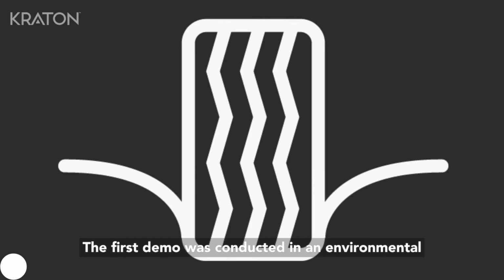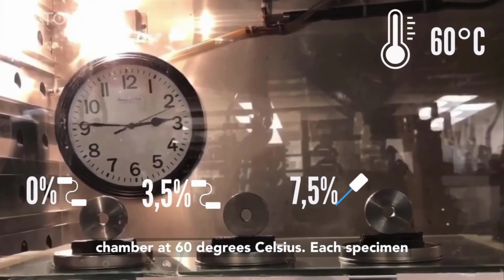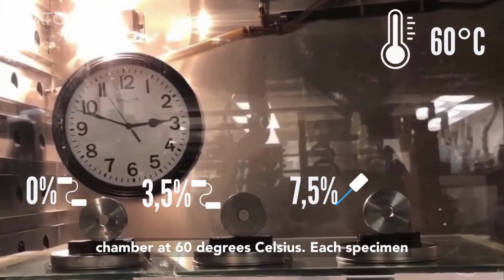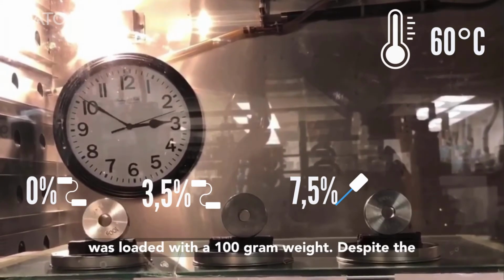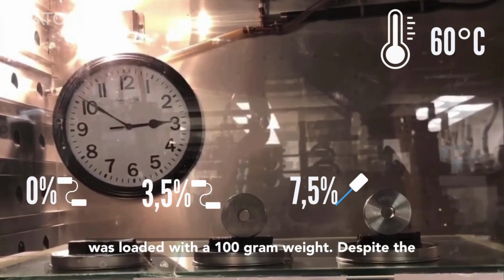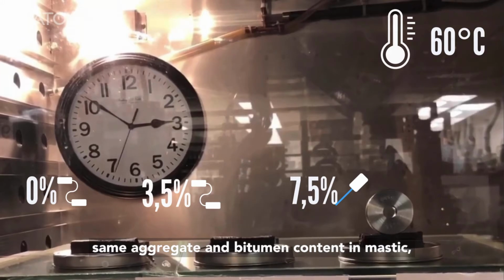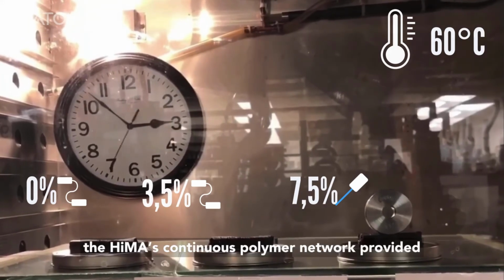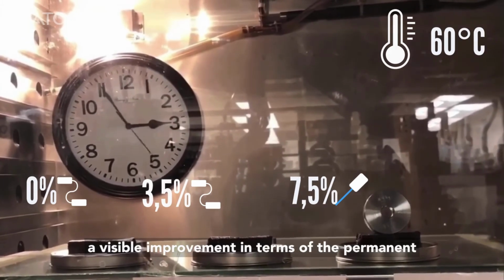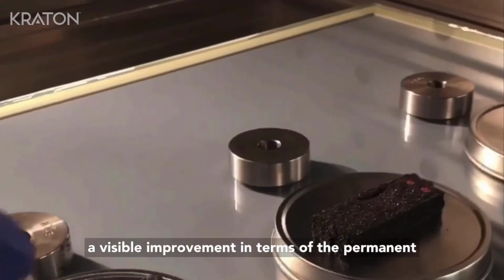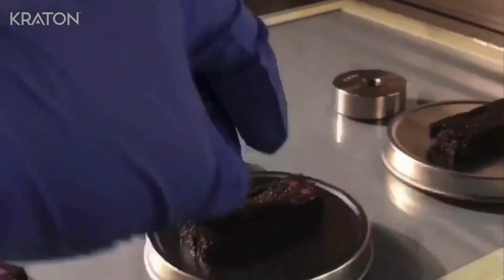The first demo was conducted in an environmental chamber at 60 degrees Celsius. Each specimen was loaded with 100 gram weight. Despite the same aggregate and bitumen content in mastic, the HiMA's continuous polymer network provided a visible improvement in terms of the permanent deformation resistance.